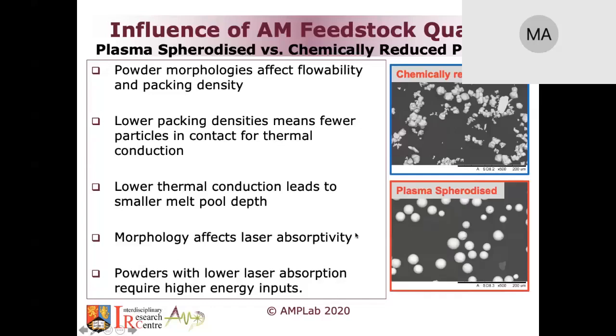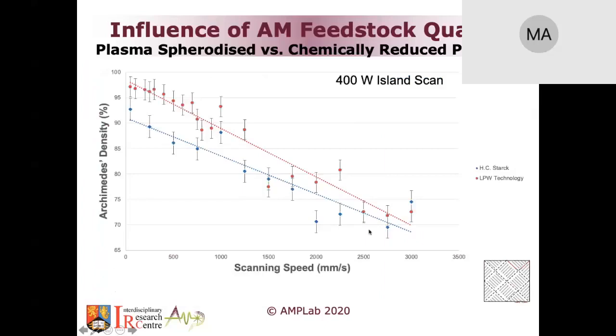Now the question is, did it matter? That's the key point I have for you. When we did the processing, we kept the laser power at the maximum, 400 watts. We used the standard island scan strategy for the machine we have. And as you can see, we had to go to very low speeds to get high density, really, really low speeds. When tungsten is melting, it's glowing so brightly that you have to wear safety goggles to watch it as it's being processed.